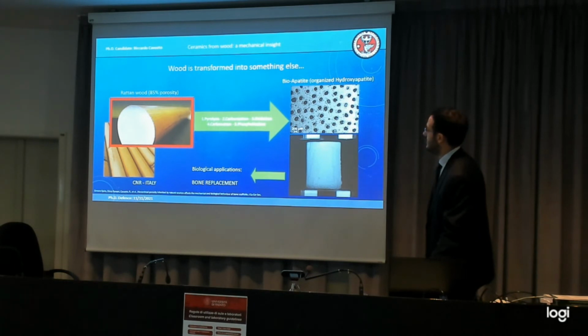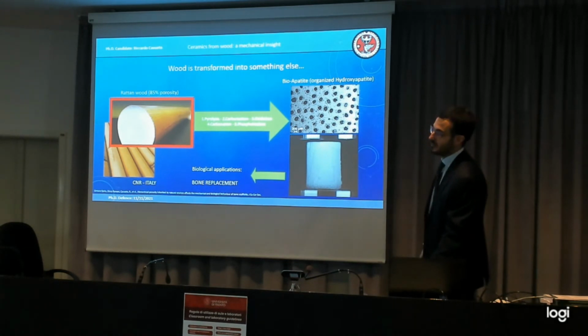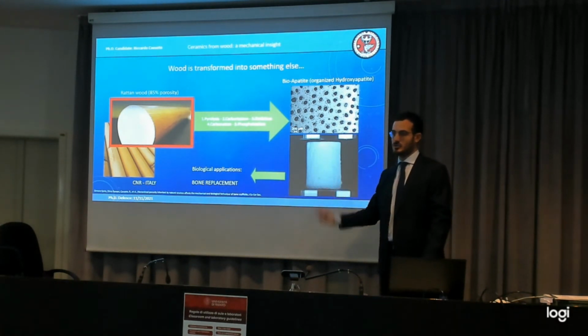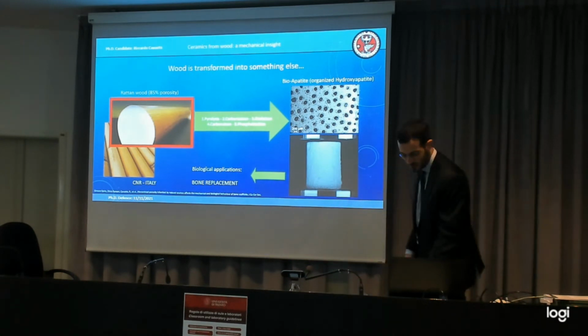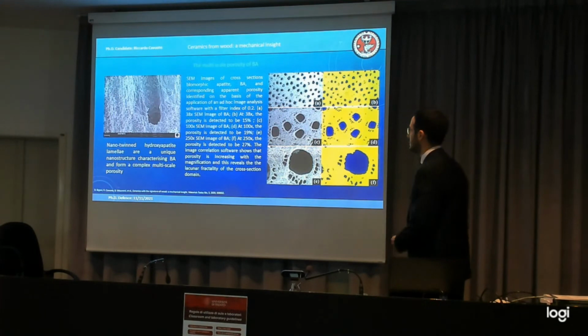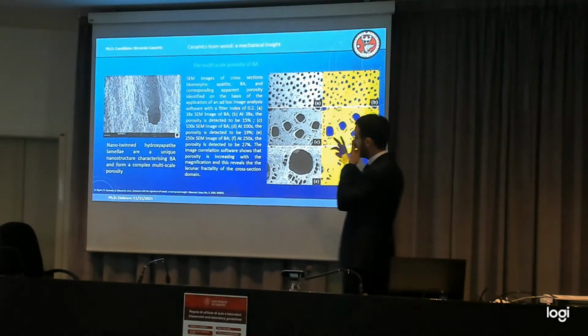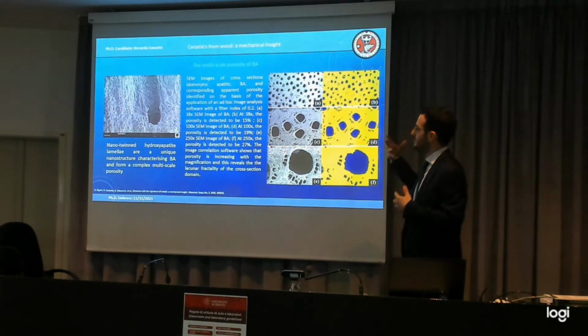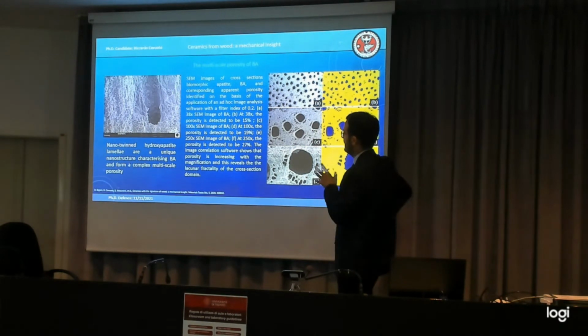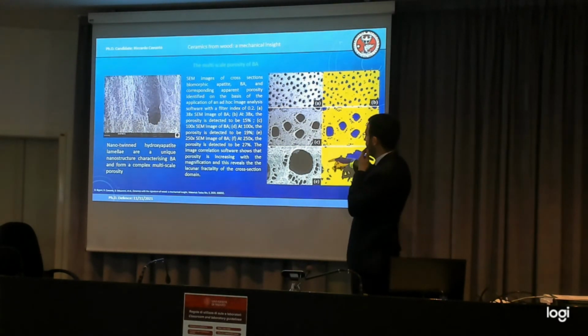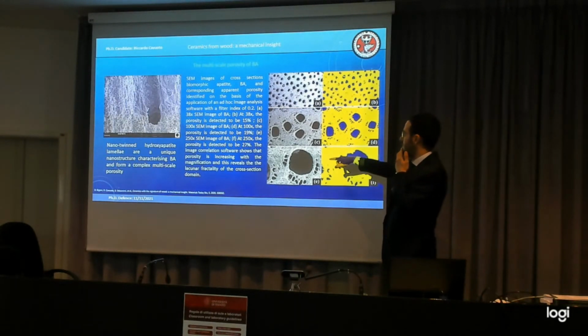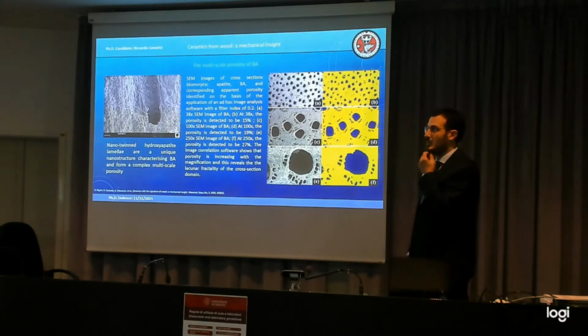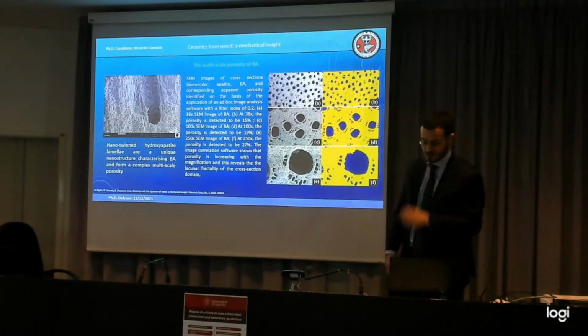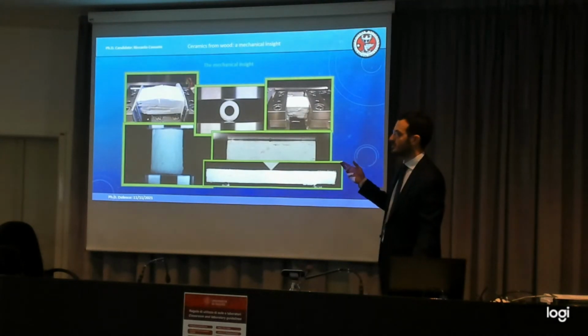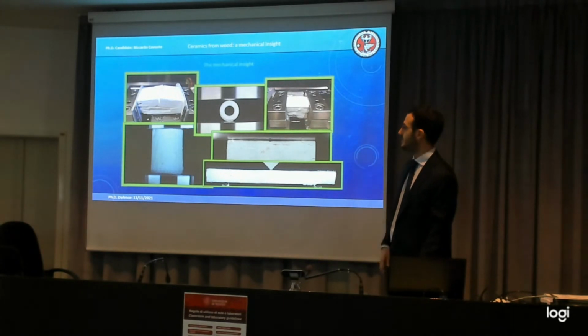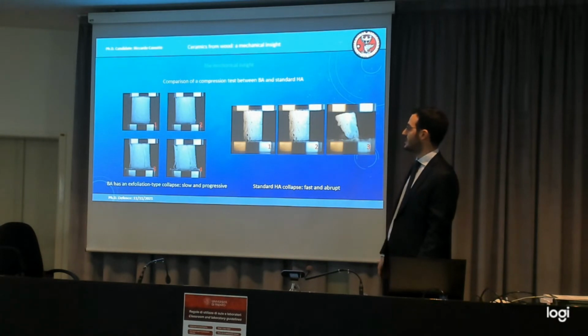So here at the university we have tested the mechanical behavior, since it's thought for bone. Biocompatibility, I mean also induction, conduction, and integration, is not the only problem that you have to deal with. You want something that is strong enough to lift the weight of the body. And this is the analysis of the porosity, which is actually what drives the main cause for the second part of this study. And as you can see, the material is of a lacunar nature. There are multiple levels of porosity ranging from a couple of micrometers to hundreds of micrometers. These different levels of porosity are actually responsible for the strange behavior that the material has under compression, and this is the result of some compression tests performed.